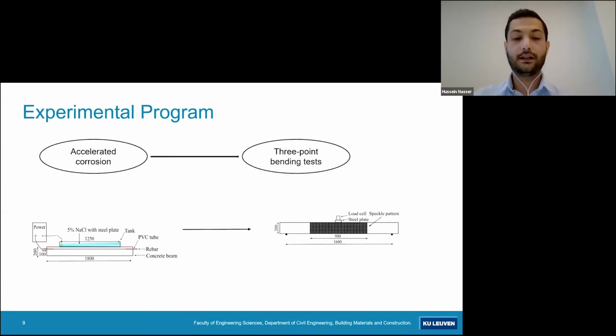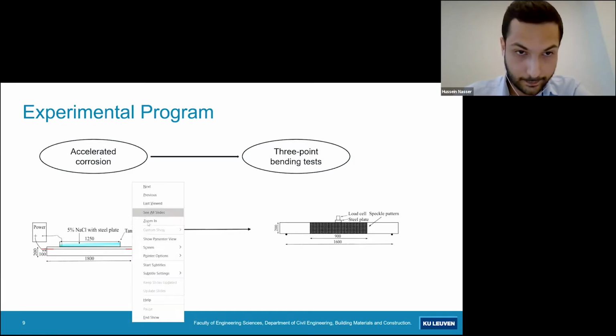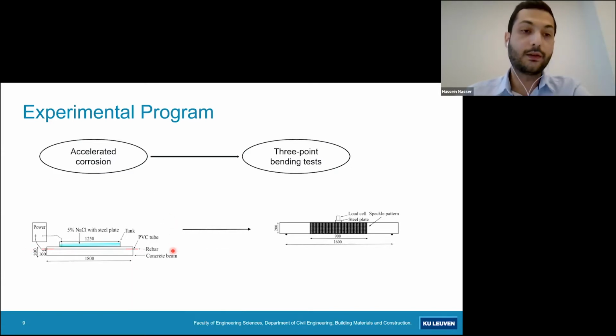Before starting with the numerical results, I will first explain the experimental program. The experimental program consists of 2 parts. The first part is an accelerated corrosion experiment, where the beams are reinforced with only 1 rebar, the rebar diameter is 14 millimeters and the cover depth is 13 millimeters. The beams, as shown in the first figure, are corroded upside down, meaning that the cover is at the top.